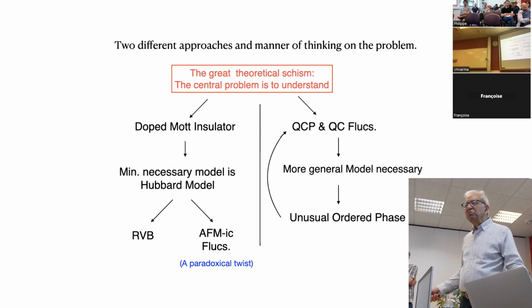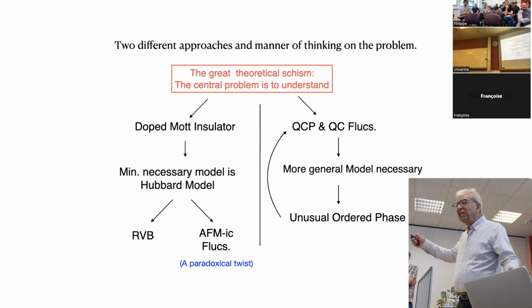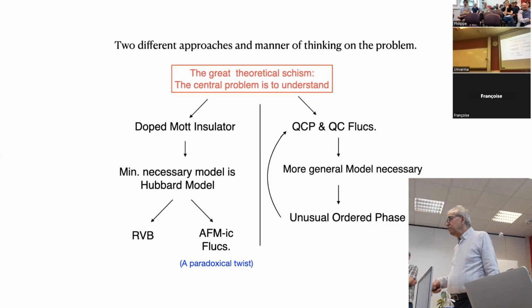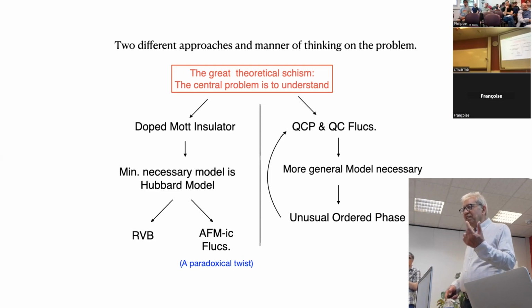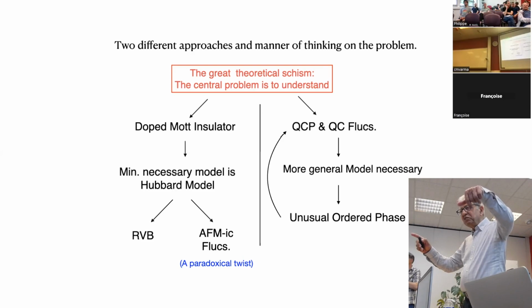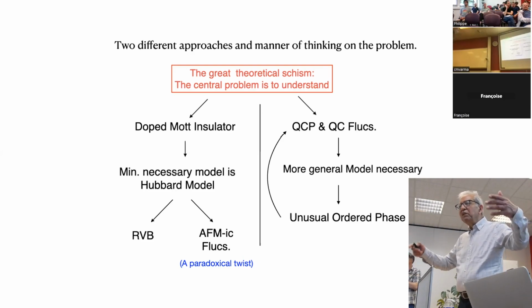So the first remark was, this is just like heavy fermions, and we know that heavy fermions have an antiferromagnetic quantum critical point about which there is superconductivity of the d-wave variety. And they have linear in T resistivity and T log T specific heat or thermal power. So what's happening? That's an antiferromagnetic point, and this I say is not, because antiferromagnetism is well separate.